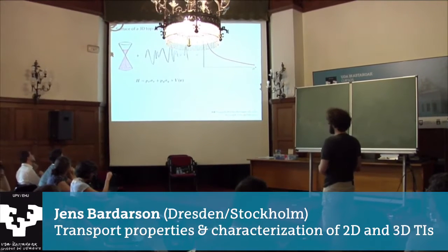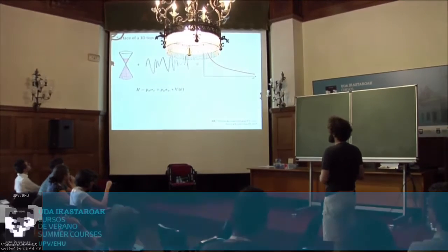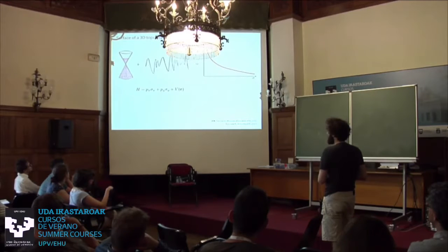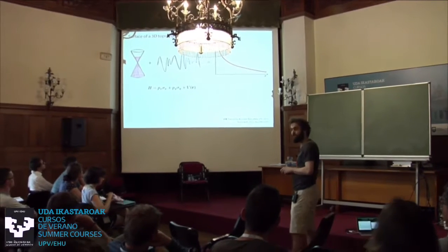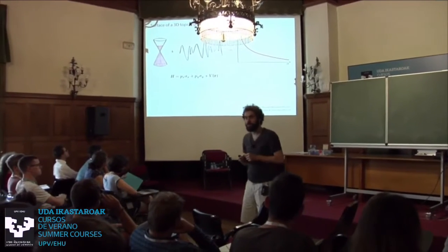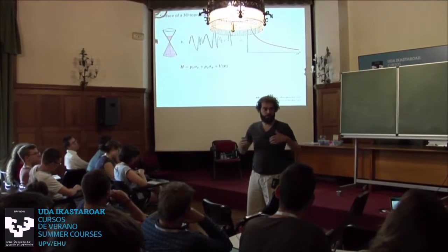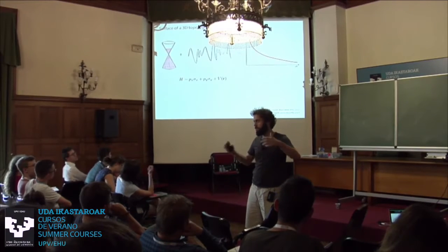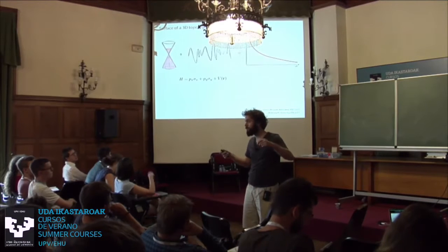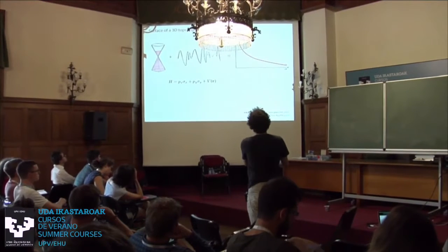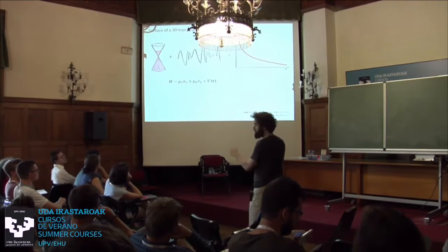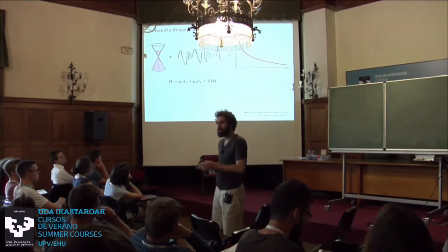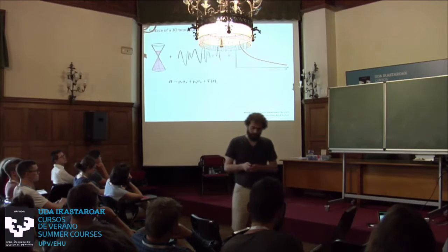And this is what we found. A Dirac cone plus disorder gives us a positive beta function, which we now all understand what that means. It means that the surface, as I make it larger and larger, has higher and higher conductance, and it flows into this symplectic metal. I call it symplectic metal because T squared equal to -1 is the symplectic class.